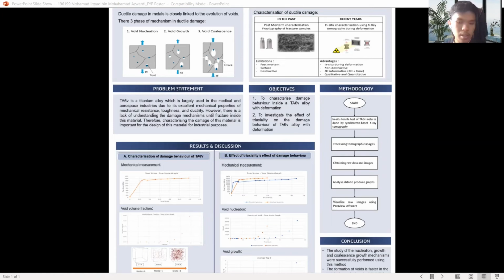So there are two objectives in this research. The first one is to characterize the damage behavior inside a Ti-6Al-4V alloy with deformation. And the second one is to investigate the effect of triaxiality on the damage behavior of the alloy with deformation. For the methodology, I started with the in situ tensile test of the metal, and then it goes to the processing of the tomographic images. After that, we obtain raw data and images in the form of qualitative and quantitative information. Then we analyze the data to produce the graphs, and lastly, we can visualize the raw images using software.